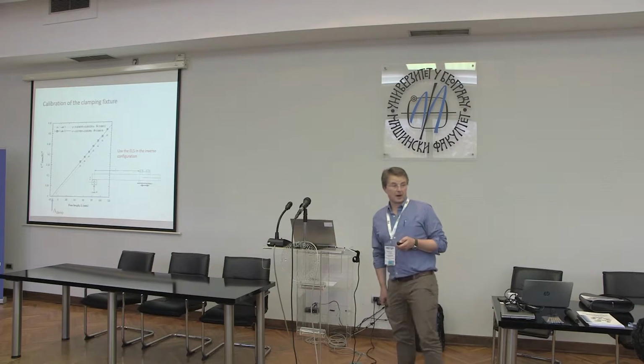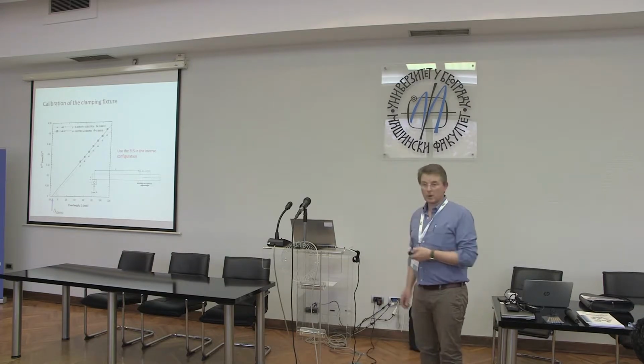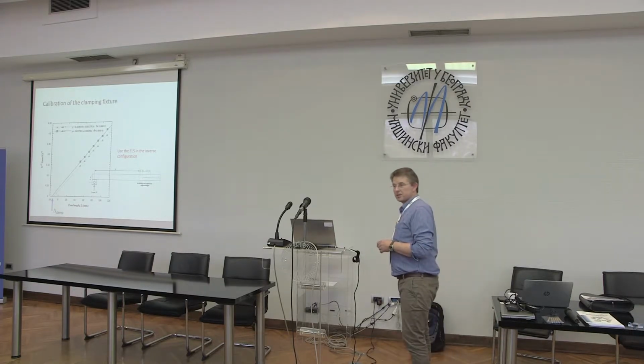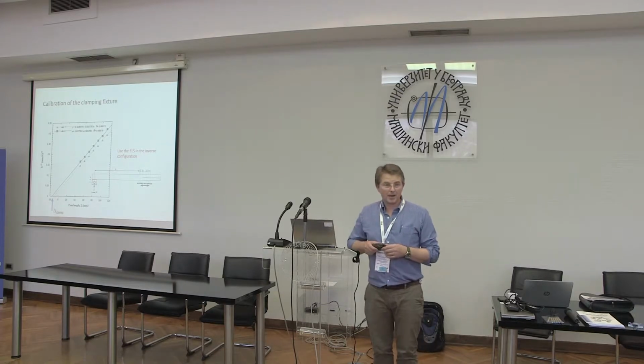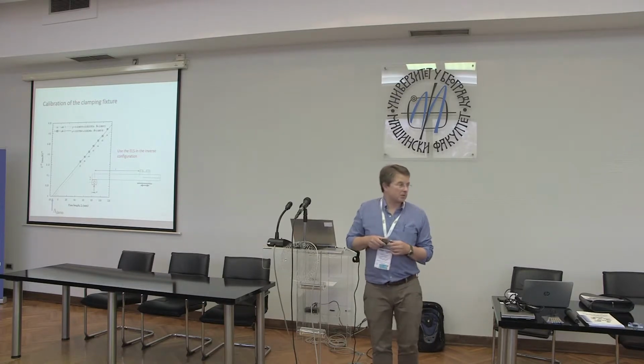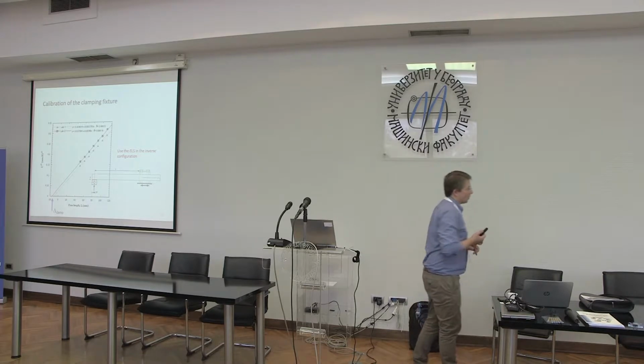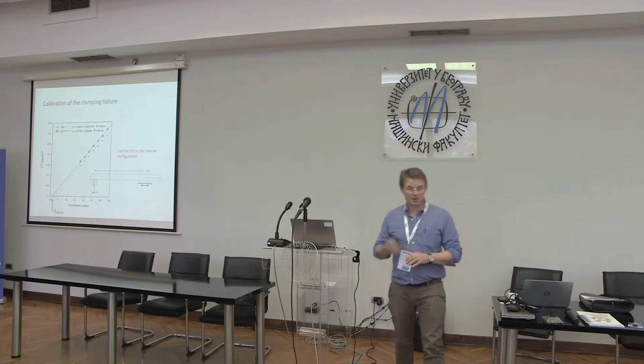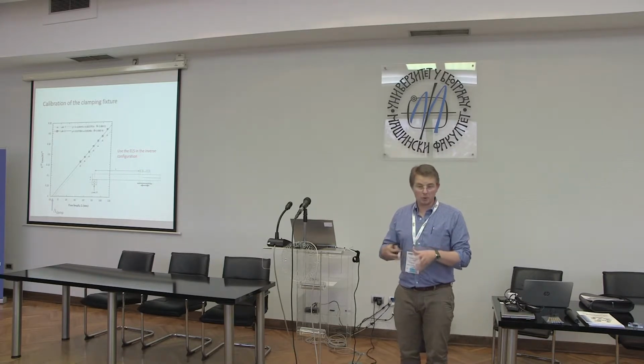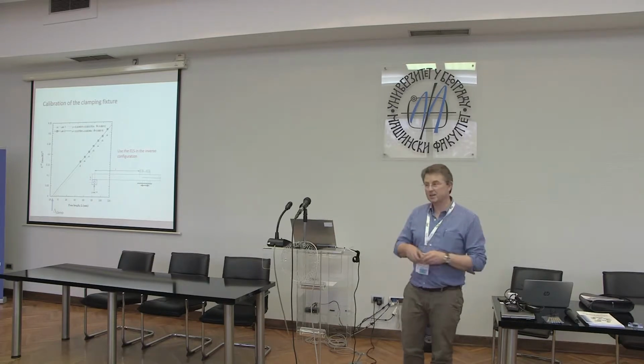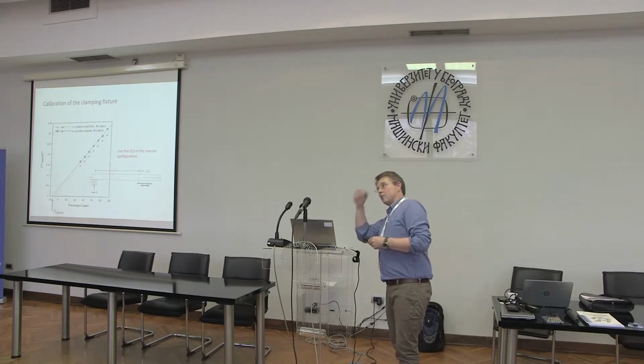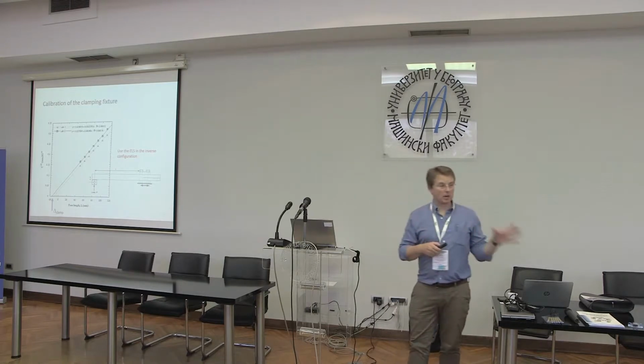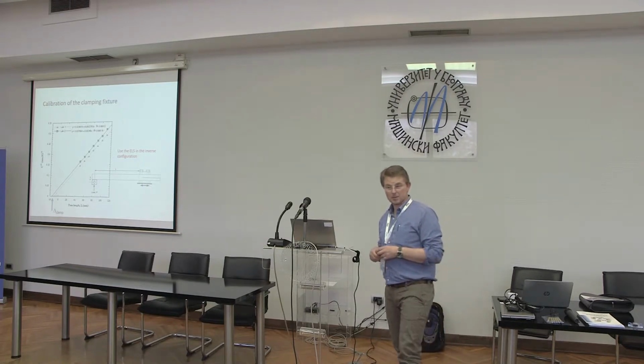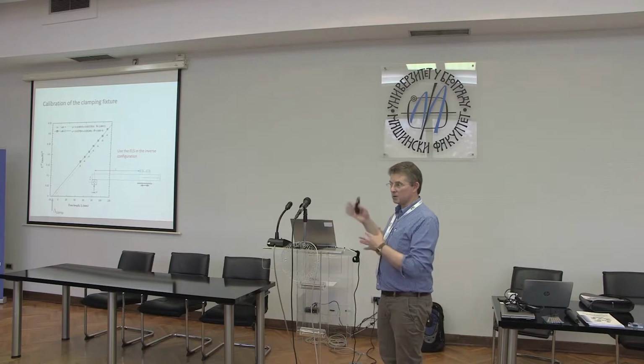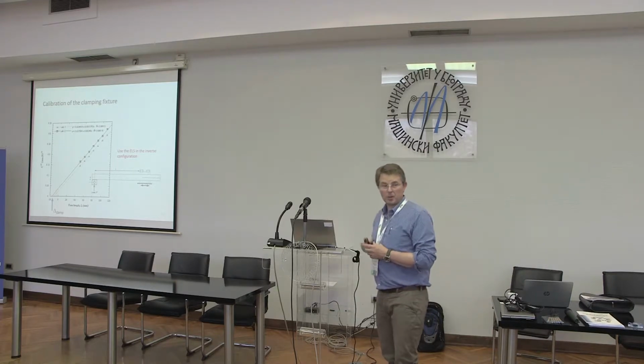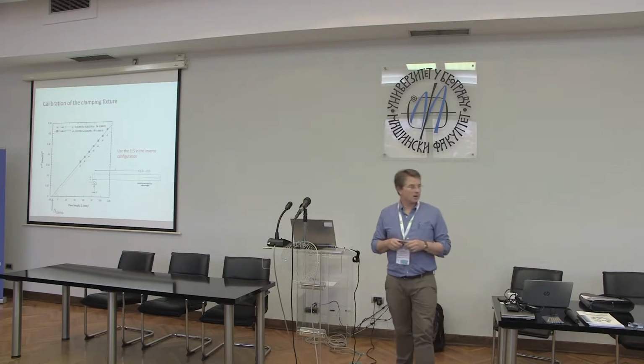That would be an effective crack length. The problem we had with this approach was that we were using a clamp. Point number one is that whenever you clamp a specimen into a system like this, you might not do it repeatedly yourself. And secondly, if you're trying to measure the reproducibility, i.e. one lab to another lab, they're going to have different clamps. And you're going to have lots of different effects on the compliance, which is very hard to rationalize.